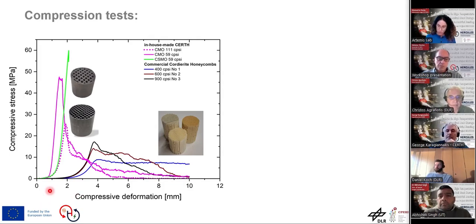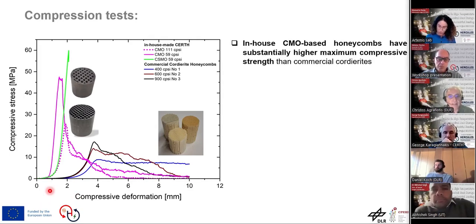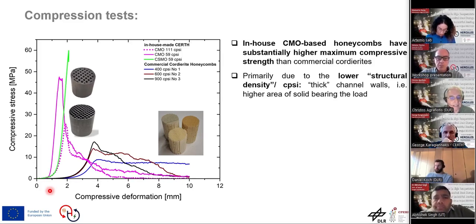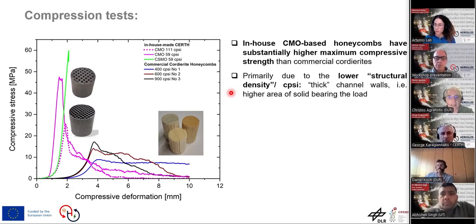If we click once or twice more, we see, for instance, our in-house synthesized honeycombs versus commercial cordierite ones. And what we can see here is that the in-house have much higher strength, which is primarily due to their thicker channels. They have a lower number of channels per square inch than the commercial ones. As you can see there, the commercial ones have an order of magnitude more. And of course, this means that the solid surface that bears the load is higher in the case of our specimens, so that's why they have a higher mechanical strength.